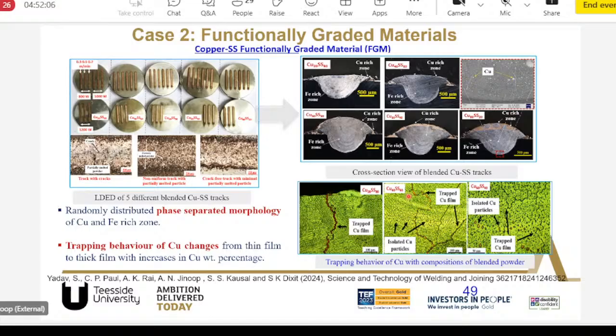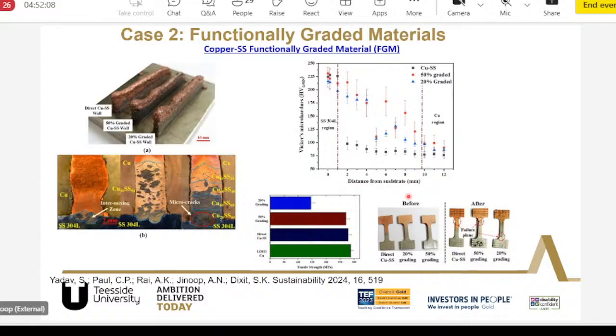And we could develop these sorts of wall structures from here. We could start from stainless steel and go to pure copper with a gradual change in the mechanical properties. You can see here how in the copper stainless steel direct joint, the mechanical properties at the interface have changed drastically, while you can see the gradual change when we do the FGM.